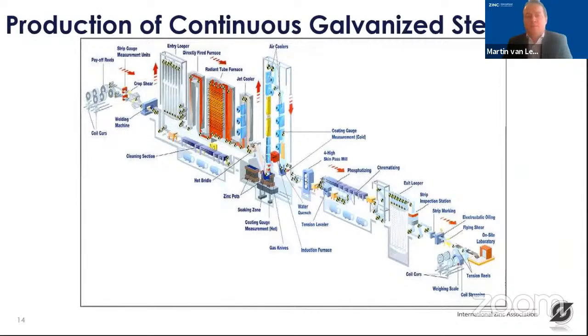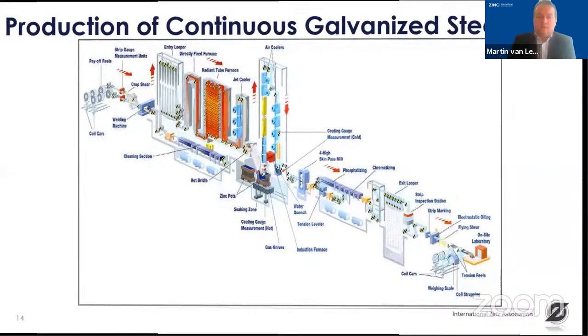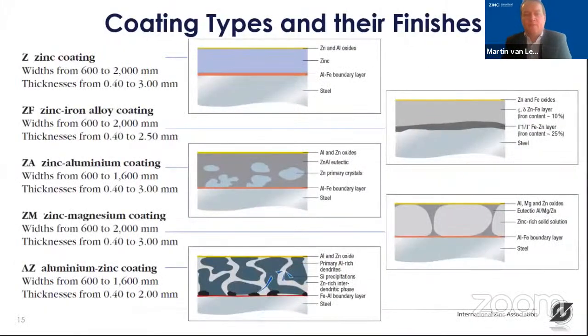After the zinc bath, the coating can be annealed as well to produce galvannealed coating instead of galvanized coating. And then you have a section with surface improvement. You can apply some oil on the surface to protect the zinc from further corrosion. Or you can also apply a top coat or a paint on top of the zinc to apply in the end a duplex coating on the steel, for example, for construction products. So this process can apply different types of coatings.